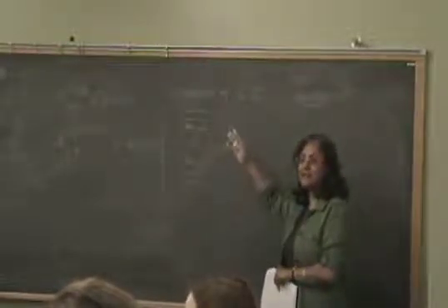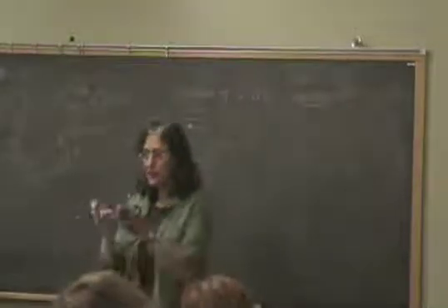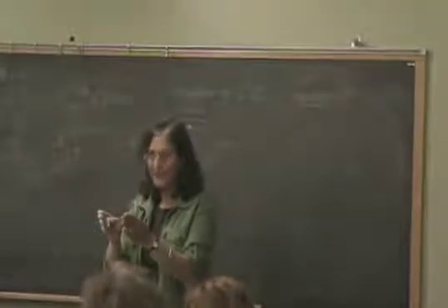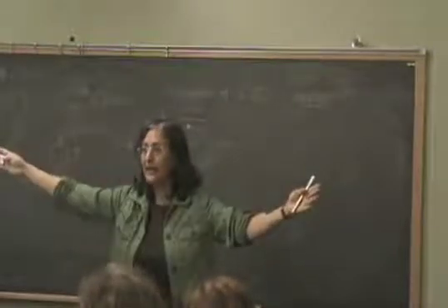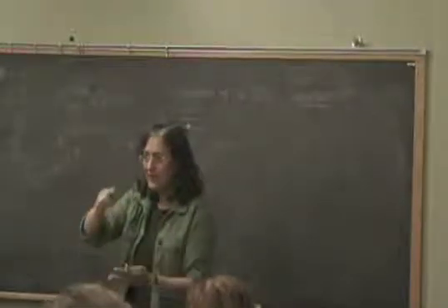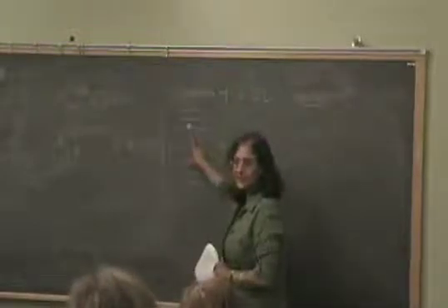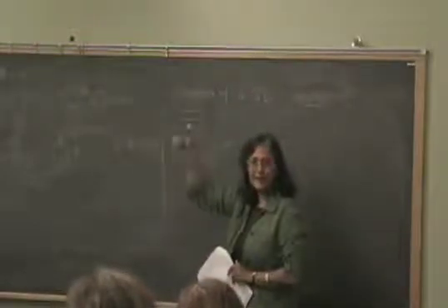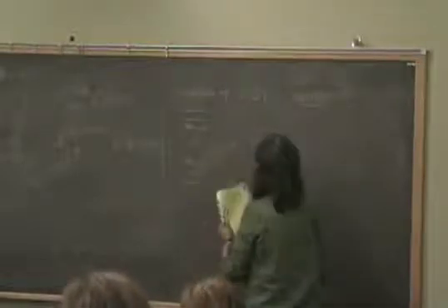So that's the reason they are very dominant, because once you have a dot, you already have a cutoff on the size of the exciton. It can't go flying anywhere. It's confined in the dot. And that makes it more localized as opposed to an exciton in the bulk. Is that clear? Okay. So let's just write this down.